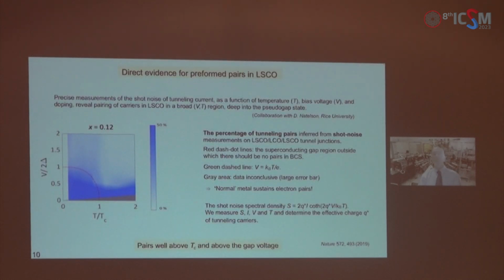Okay, so one more probe was shot noise spectroscopy in high-Tc tunnel junctions made of normal metal and cuprate superconducting electrodes. Shot noise spectroscopy is arguably the most direct probe of the charge of mobile carriers. You may remember that Laughlin got the Nobel Prize for predicting fractional charge excitations in the quantum Hall effect only after charge 1/3 was observed by shot noise spectroscopy. In lanthanum strontium cuprate, we observed charge 2e, the pairing, but up to temperatures that were way above Tc. And even more extraordinarily, we see pairs also at bias voltages which can be 2 or 3 times larger than the apparent superconducting gap. I don't know what this means, but what we do know is that this is nothing like BCS.